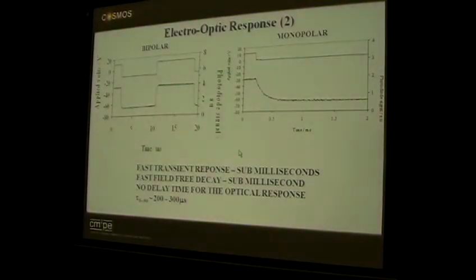To prove something that is important for a device engineer: I said the effect was independent of voltage or field. It's a materials parameter. If you take the voltage off, as you do there, is the response time just as fast? And the answer is yes, it is. That time is as fast as that time. That's the 10 to 0 volts. And no matter what level you switch from, you always see the same response time.